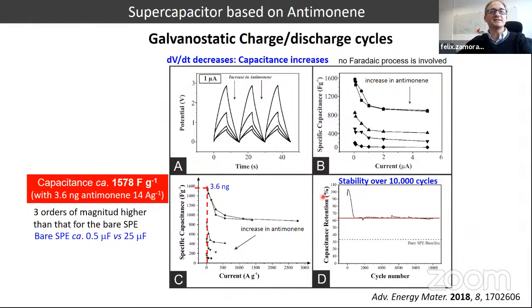In order to get a more realistic value of capacitance, we performed galvanostatic charge-discharge cycles, trying to avoid the Faradaic contribution of the other process. And then we carried out these experiments in which we observe again that as you increase the quantity of antimony, the potential decreases. And we end up with the optimal value of antimony to have a good specific capacitance for our modified electrode, 3.6 nanograms. Additionally, you can observe that the modified electrode is pretty stable, stable over 10,000 cycles, which is quite remarkable.